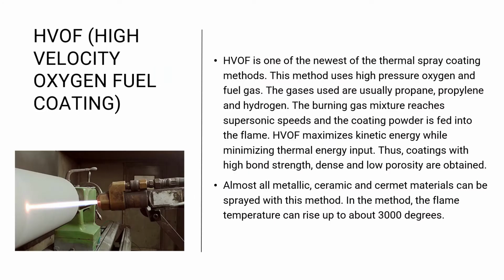And so let's talk about high velocity oxygen fuel coatings. This method is one of the newest of the thermal spray coating methods. This method uses high pressure oxygen and fuel gas, and the gases used are usually propane, propylene, and hydrogen. The burning gas mixture reaches supersonic speeds, and the coating powder is fed into the flame. High-velocity oxygen fuel maximizes kinetic energy while minimizing thermal energy input. Thus, coatings with high bond strength, dense, and low porosity are obtained. Almost all metallic, ceramic, and cermet materials can be sprayed with this method. In the method, the flame temperature can rise up to about 3000 degrees.